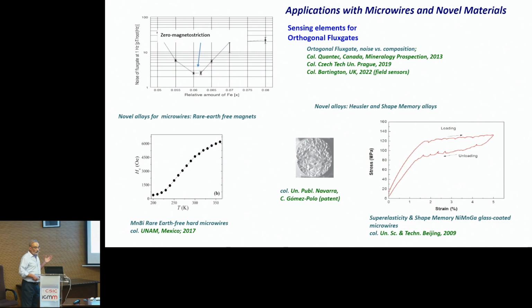But we have also had different collaborations with other groups, for example to develop microwires as sensing elements for orthogonal fluxgates. We have also developed new alloys, for example manganese bismuth rare-earth-free hard microwires. Here the important thing you see is the coercivity as a function of temperature. Coercivity is not so large, but what is important is that coercivity increases with temperature. Normally it has to decrease, but in this particular case, because of particular anisotropy, it increases with temperature.